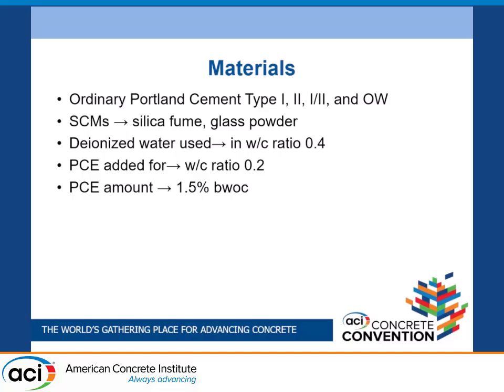For the squeezing, we only used water cement ratio of 0.2 because we are targeting our study towards UHPC, and the squeezing apparatus gives better results with low water cement ratio. But for one comparison, we did one sample with 0.4 water cement ratio for the squeezing as well.